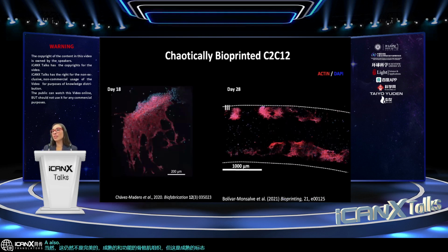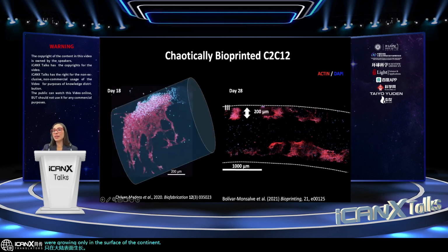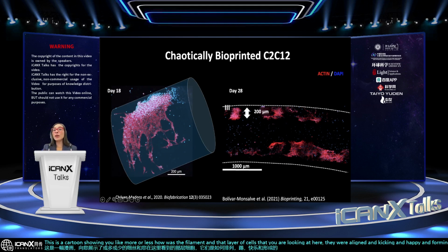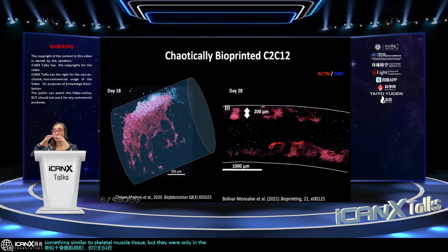Although there is a problem here, because we realized that the cells were growing only on the surface of the construct. This is a cartoon showing you more or less how the filament was, and that layer of cells that you are looking at here, they were aligned and kicking and happy and forming something similar to skeletal muscle tissue, but they were only on the surface of this big construct of 1 millimeter thickness.